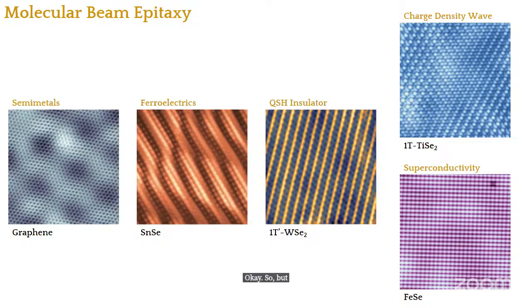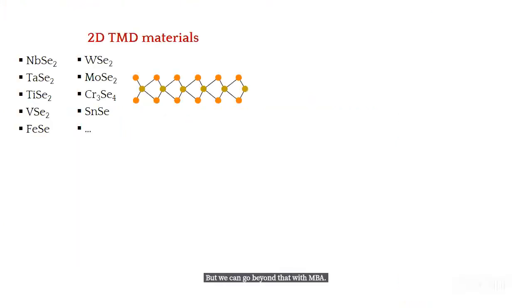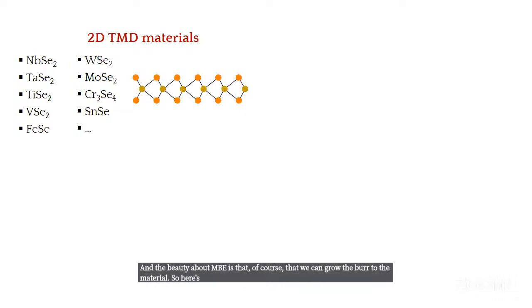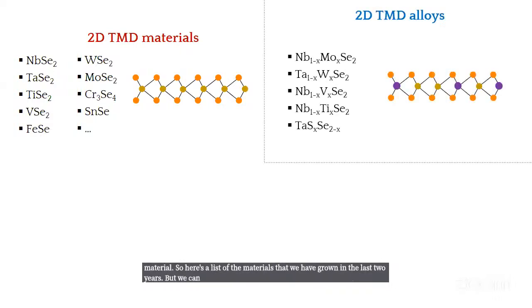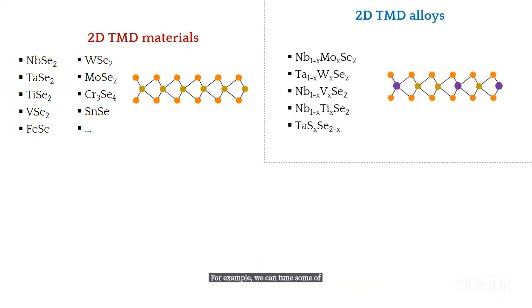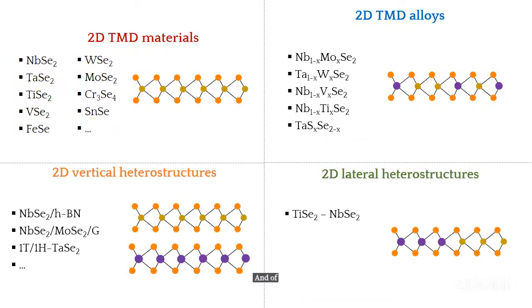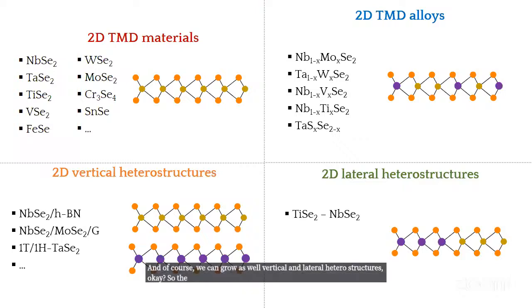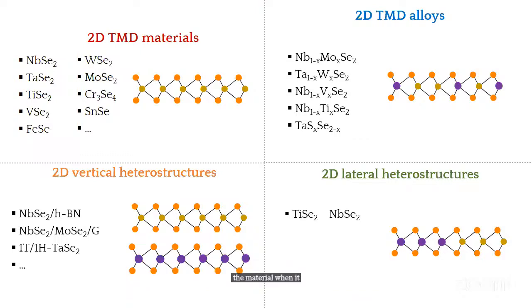So, but we can go beyond that with MBE. And the beauty about MBE is that, of course, we can grow the bare 2D material. So here's a list of the materials that we have grown in the last years, but we can go beyond that. For example, we can tune some of the properties of the material by growing alloys. For example, mixing niobium and molybdenum. I will show you in a second a little bit about these experiments. And of course, we can grow as well vertical and lateral heterostructures, okay? So the properties of these individual materials are different from the material when it's stacked in a vertical position. I will show you an example of this as well.